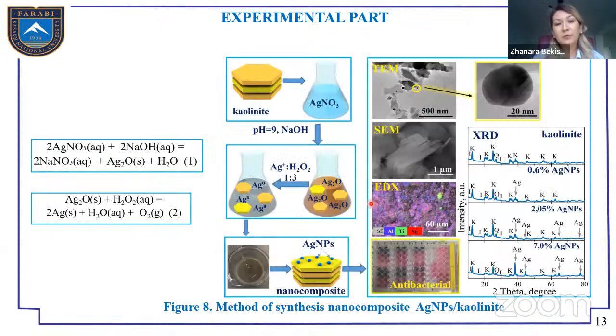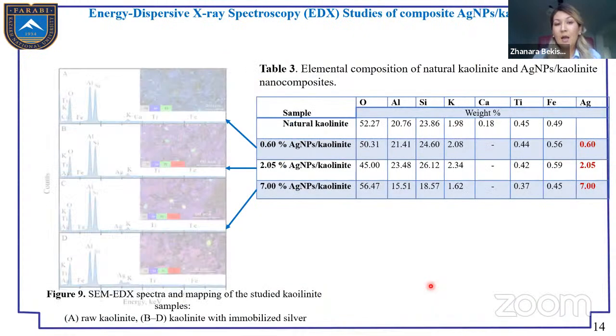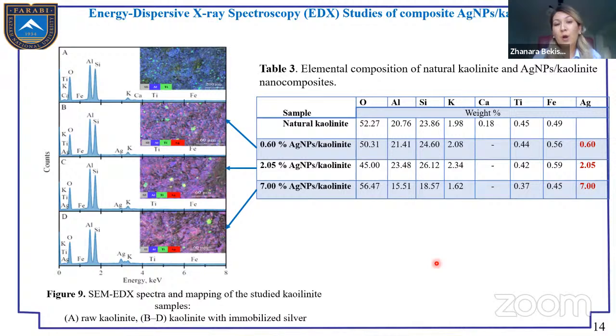In the experimental part, for the synthesis of the silver nanoparticles-kaolinite composite, the kaolinite was impregnated with silver nitrate solution, basified, and reduced with the environmentally friendly hydrogen peroxide reducing agent. Then it was washed and dried at a temperature of 110 degrees. We studied the physical-chemical properties of the obtained composite and its antibacterial activity. The initial concentrations were 1, 5, and 10%, and the adsorbed silver was 0.6, 2.05, and 7% of silver in the kaolinite composite.